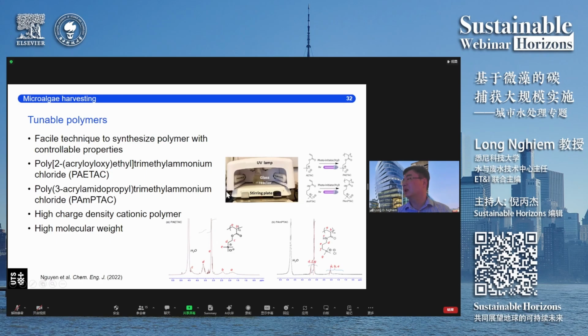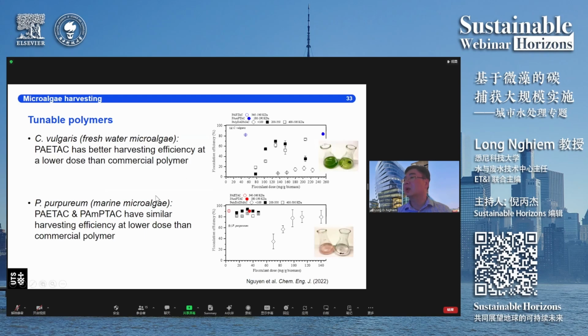Now, the beauty of this simple process is the fact that we can regulate the molecular weight and the charge density of the polymer by controlling the monomer concentration as well as the UV power. So we have tested the method with two polymers called PAETAC and PAmPTAC, and then we contrast our polymer with commercially available polymer. And you see that our polymer, on the top figure highlighted in blue here, have much higher harvesting efficiency, or in the case of the other species, red microalgae, our polymer have the same harvesting efficiency, but require a much lower dose. So in this case, the PAETAC only requires about 5 milligram per gram of biomass. So this is really, really low dose.